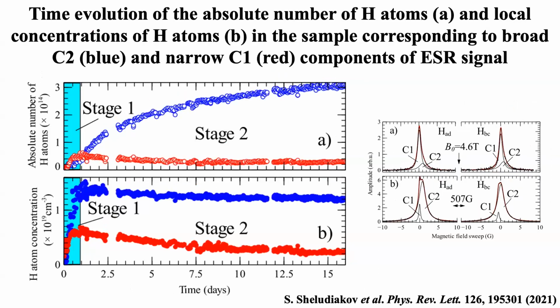So first we analyze these two lines, broad and narrow. This is the dependence of the number of spins determined from the broad line, and this is the number of spins, or atoms, determined from the narrow line. We decided it's a small addition from the narrow line, so we analyze really by using one Lorentzian line, analyzing only the broad line in the following.